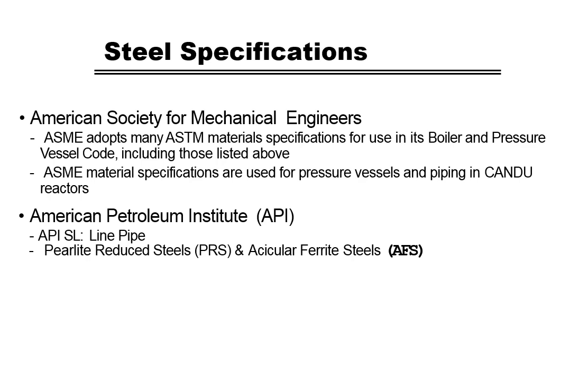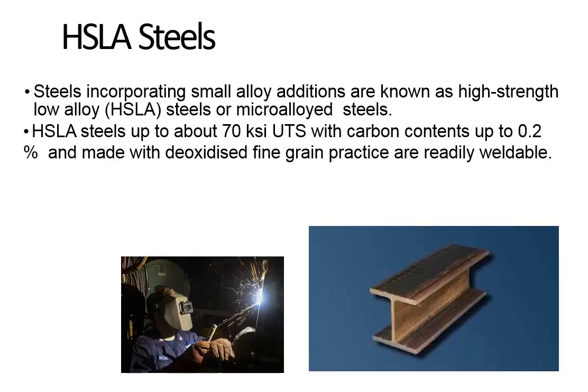So these are some steels you might want to look at at some point if you're building something and you need pipe. High strength, low alloy steels. Steels incorporating small alloy additions are known as high strength, low alloy steels or microalloyed steels. High strength, low alloy steels up to about 70 KSI ultimate tensile strength with carbon content up to 0.2% and made with deoxidized fine-grained practice are readily weldable. So there's a whole list of high-strength, low-alloy steels that are readily weldable. Just need to follow the directions and make sure your workforce is on board with what you're doing, and generally shouldn't be too much of a problem to weld this stuff.